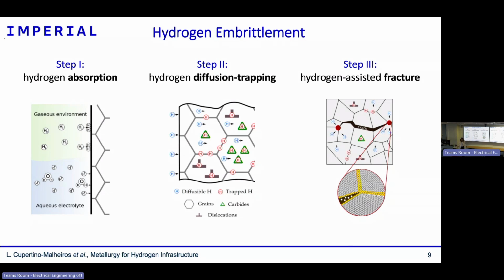with coating, and I think something that we all consider a bit dangerous, is that coatings can, and usually do, if you are talking about infrastructure that will stay there for many years, present defects. And as soon as there is a defect, you are exposing your weak bulk material. If your material is not resistant to hydrogen embrittlement, it can be quite dangerous to only rely on coating. So in my personal opinion, you can use coating, but you should also aim for a material that has a good resistance to hydrogen embrittlement.